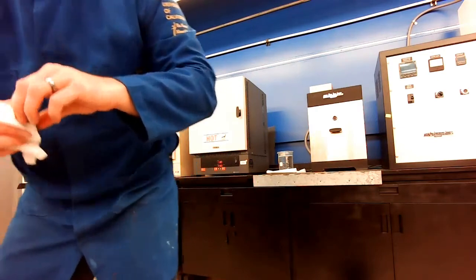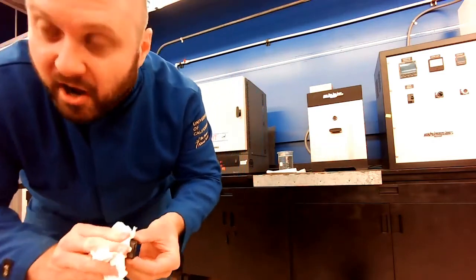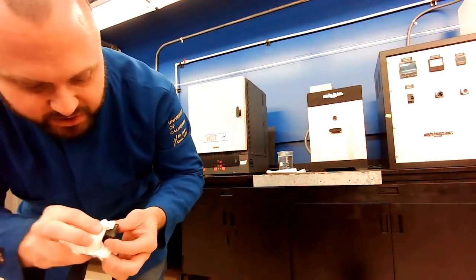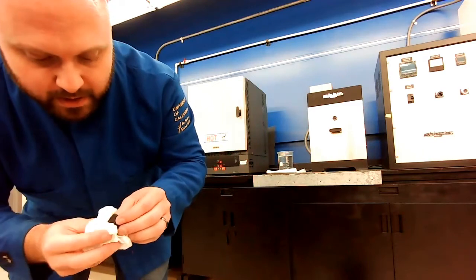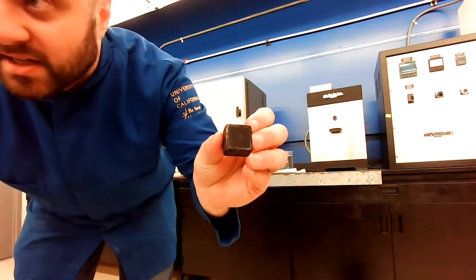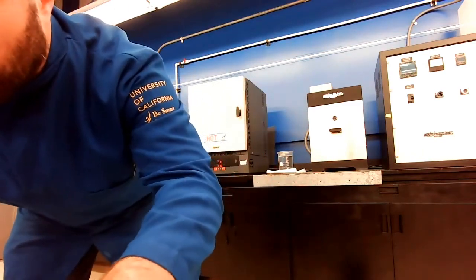I'm not too worried about making it perfectly cleaned off right now because I'm going to have to polish this sample again. Here you go. You can see that second one. So right now, these should have identical microstructures. They should both be a fine martensite because they were rapidly cooled down. And then we're going to take one of them and try to coarsen that martensite with the tempering procedure.